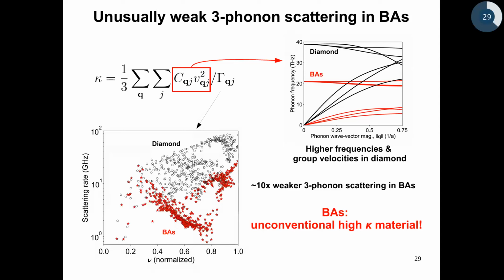But if you look at the denominator, that is the scattering rates, in this case the 3 phonon scattering rates, what they found was that the 3 phonon scattering rates for boron arsenide were unusually weak, almost 10 times weaker than that of diamond in this small frequency range. So this means that the denominator is smaller for boron arsenide than for diamond. By having a smaller denominator, boron arsenide compensates for the smaller numerator, and eventually the thermal conductivity of boron arsenide even exceeds that of diamond at room temperature. So this shows that boron arsenide is achieving this high thermal conductivity in an unconventional manner, defying the conventional guidelines. So what causes these unusually weak 3 phonon scattering rates in boron arsenide?